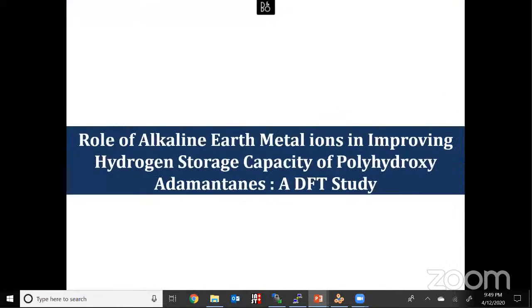Yeah, so compared to anionic as well as cationic clusters, we found that cationic clusters are good enough to store hydrogen, trapping hydrogen molecules with the required binding energy, and if the substrate is low molecular weight, that will help to improve the weight percentage. So in this one, I chose polyhydroxy adamantane and introduced open metal sites on the polyhydroxy adamantane unit and calculated their hydrogen storage property. So for that, I had used.